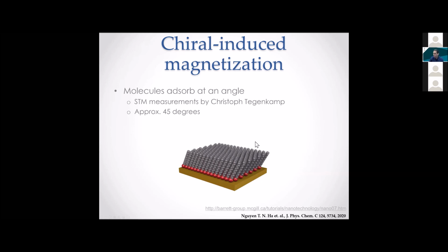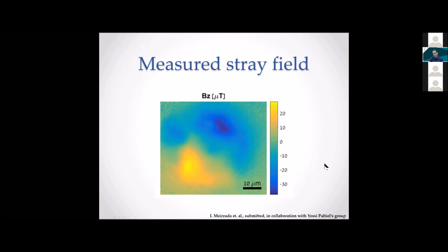Prior to our results and to these recent measurements by the Tegenkamp group, we were unaware of this tilt angle, and we had this notion that the adsorption was perpendicular to the surface. So the results that I'm showing here are essentially measurements performed using this magnetic microscope, depicting a spatial image of the stray field created by the sample and measured by these NVs.